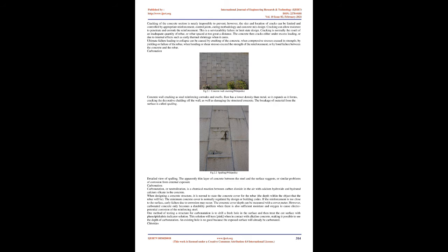As a rule of thumb, only to give an idea on orders of magnitude, steel is protected at pH above 11 but starts to corrode below 10 depending on steel characteristics and local physico-chemical conditions when concrete becomes carbonated. Carbonatation of concrete along with chloride ingress are amongst the chief reasons for the failure of reinforcement bars in concrete.